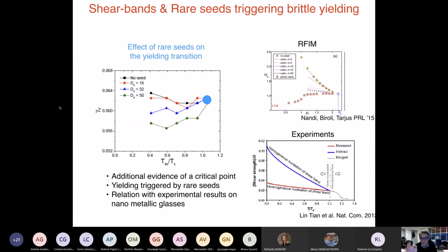The more disordered means the higher the temperature at which I prepare the system. You see the effect decrease, and then at a certain point, which is this dot, when T init is equal to Tc, where Tc is the temperature corresponding to the critical point separating brittle yielding from ductile yielding, the effect of putting a seed just disappears. So this is very similar to the random field Ising model, and really tells you that in the case of brittle yielding, what is really important are these rare seeds, and these rare seeds are related to the shear band behavior.